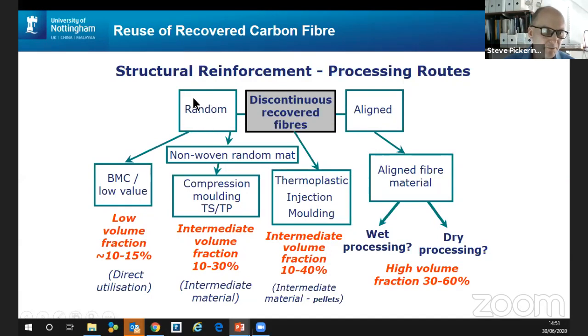Well, if we take those fibers in the random form they've been recovered, I've shown a number of applications at the bottom here, going from low fiber volume fraction on the left to a high fiber volume fraction on the right. So these are where you're using the fiber as a structural reinforcement in new polymer composites. You could put these random fibers directly into a bulk molding compound, and that would be an easy thing to do, but you'd only get very low fiber volume fractions, 10 to 15%, and these are not really very high grade in their properties.